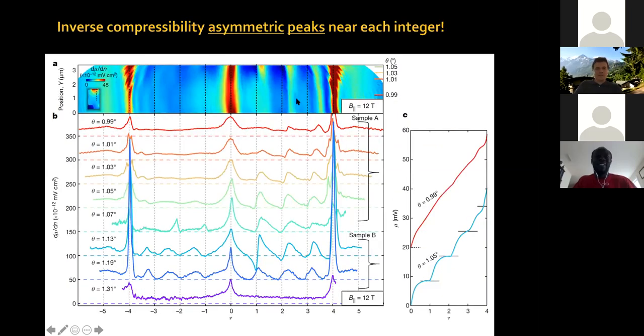So now, let me show you some more data at lower temperature. Again, the x-axis is now normalized to filling factors, so all of these lines are aligned, even though the twist angle is changing in these different positions. So you can see the actual traces here. You can see, for example, that for a twist angle of 0.99 degrees, features are very weak. You have the peaks corresponding to the band insulators. You have the peak corresponding to the charge neutrality point, to the Dirac cones. And then you see some features here, but very weak.